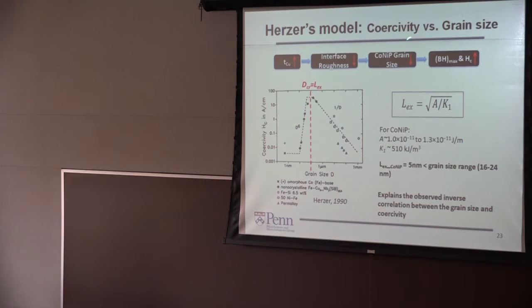The interplay between the grain size and the coercivity can be understood by a theoretical model proposed by Herzer. Basically it says that for an assembly of small grains, the competition between the anisotropy energy and the exchange magnetic energy determines whether the coercivity is proportional to d to the 6th power or 1 over d. The dividing point is when the grain size equals the exchange length. For our system, cobalt nickel phosphorus, the calculated critical grain size is 5 nanometers. As you recall, the grain size lies between 16 to 24 nanometers, which is on the right side of this 5 nanometers. So this explains the inverse relationship between the grain size and coercivity.